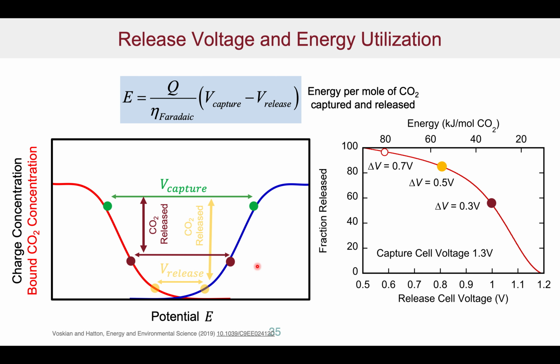In fact, if we look at the fraction released, as shown here, as a function of the delta V in the system, this is what you would get as we decrease the delta V. The good part about this is that although we're getting less utilization of the total quinone in the system, we are getting much lower energetics per mole of CO2 released. So that's a really strong plus for this particular case. And here we're well below 40 kilojoules per mole.